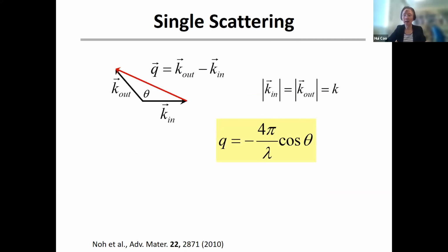But how about scattering into other angles, not in the backward direction? Say I have light coming in this way, and then the light will be scattered in another direction, which is characterized by the angle theta. Now the difference between k in and k out here still has to be provided by the spatial vector of the structure. And this will determine the wavelength of light that can be scattered into a particular angle theta through constructive interference. So with simple math here, we can see that the wavelengths for different scattering angles will be different, even though we have the same dominant spatial frequency. This is because we are illuminating at one angle and observing from a different angle. This is actually how Raman realized the color of this blue feather comes from interference.